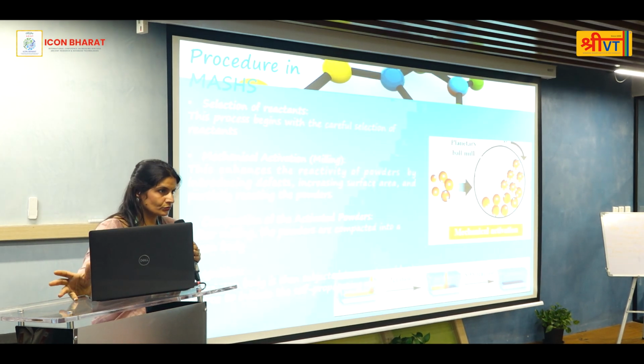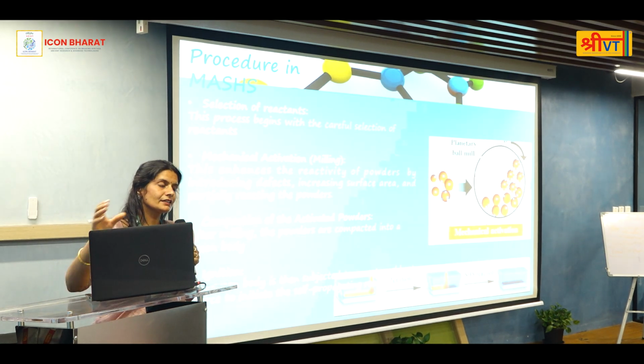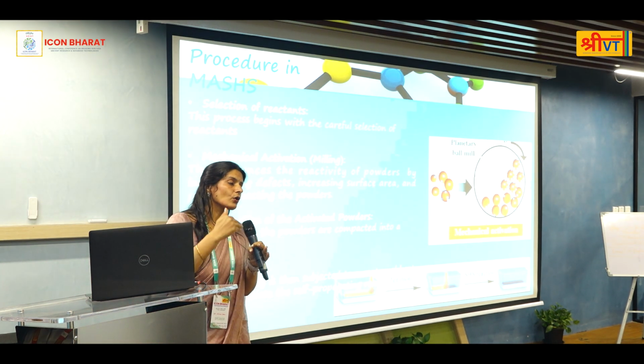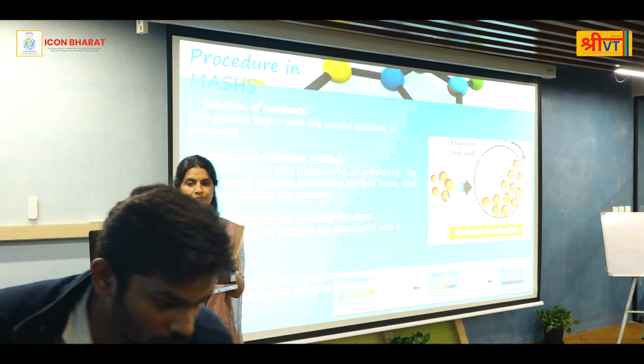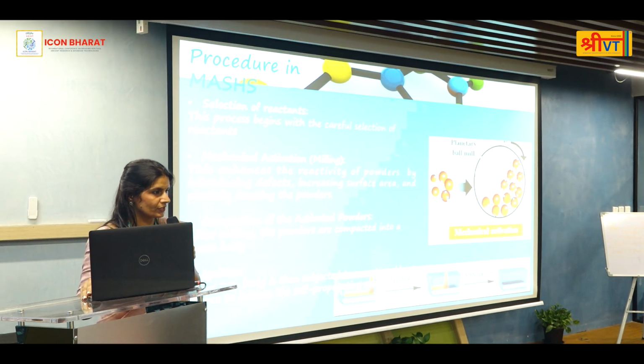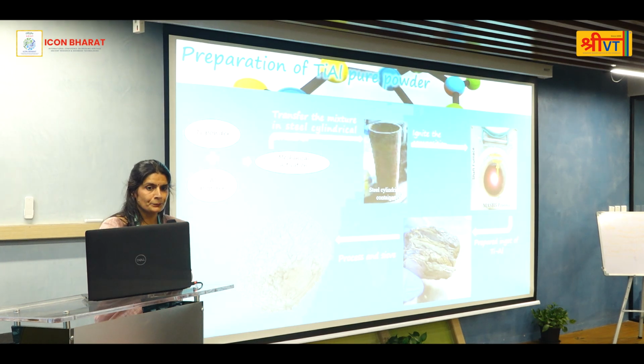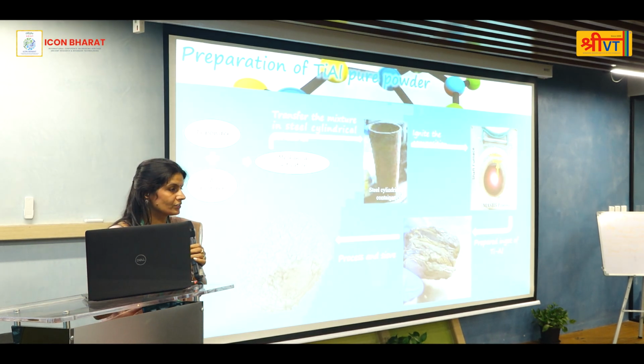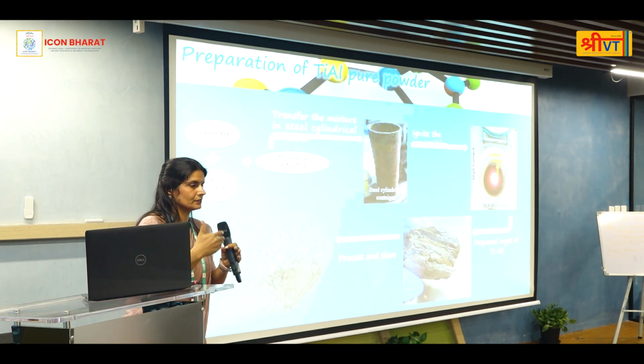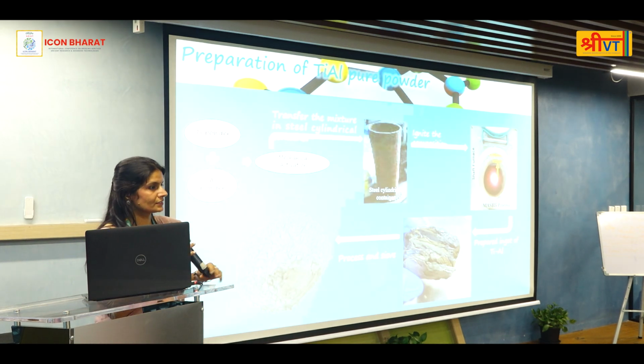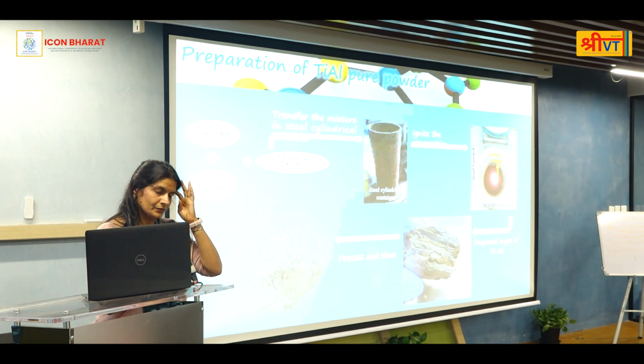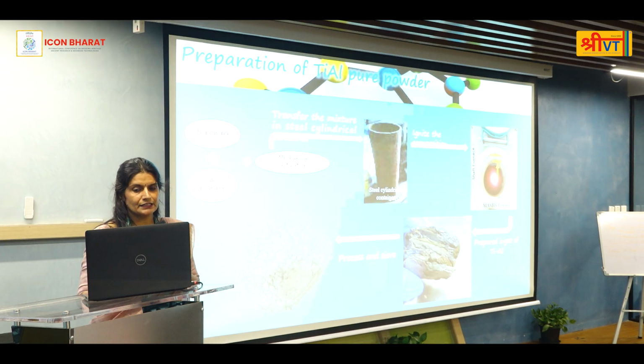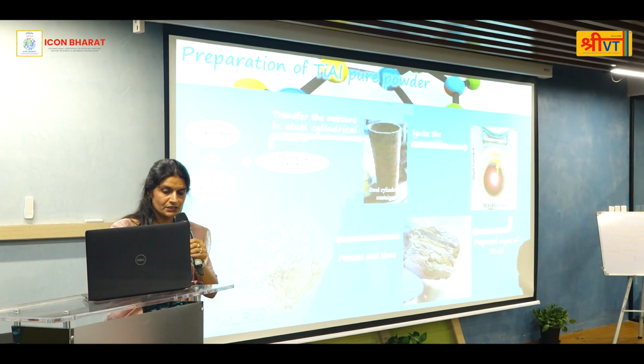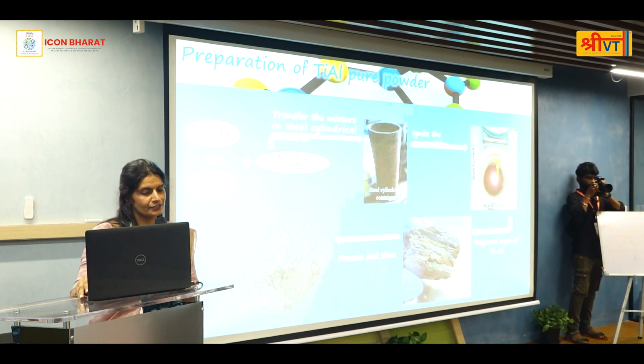The procedure involves the selection of suitable material, then mechanically activating that material, then compaction of that material in a reaction vessel, and igniting or heating the material up to the temperature for self-ignition. Then we get our final product, and we process the ingot and collect the powder. First, as precursors we use titanium powder and aluminum powder of AR grade, and then mechanical activation is done in a planetary ball mill with optimized rotation period and rotation speed. Then we transfer this reaction mixture into a cylindrical vessel, put the vessel in the shaft furnace, and ignite the powder. Then we get this kind of ingot. Then we process this ingot and sieve with the desired particle size range, and we get our final powder.